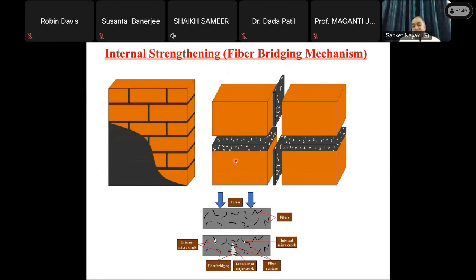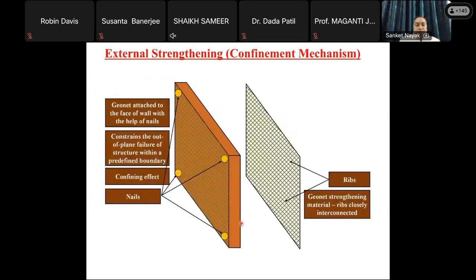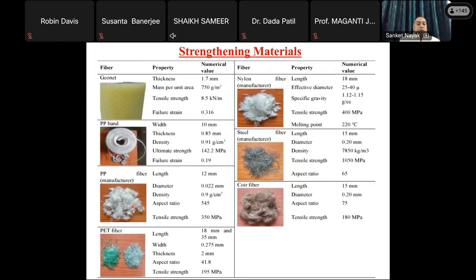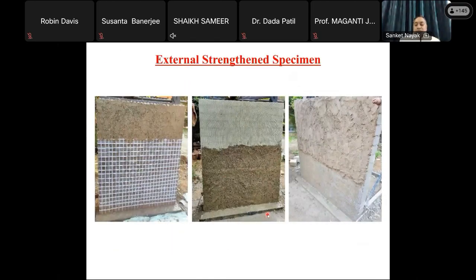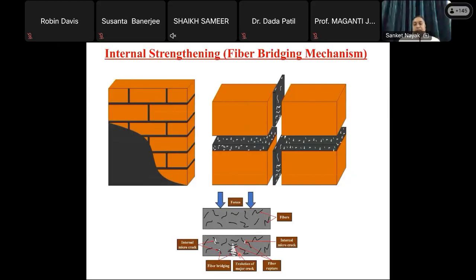This is the fiber bridging mechanism. So what happens? The mortar is added with fibers. What are the types of fibers? We have used polypropylene fibers, PET fibers, waste plastic bottle fibers, nylon fiber, steel fiber, and coir fiber. They are added to the mortar to make the matrix, and we have seen that this fiber bridging mechanism has been developed so that the initiation of the crack has been arrested, and the widening of the crack has also been restricted to some extent by the fiber bridging mechanism.